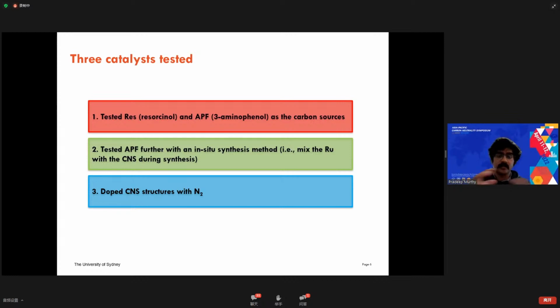Rather than directly loading the ruthenium onto the carbon, we mixed them together prior and then formed the overall catalyst that way, so it's a much more homogeneous structure. And of course, we also doped the carbon nanospheres with nitrogen, as I already mentioned.